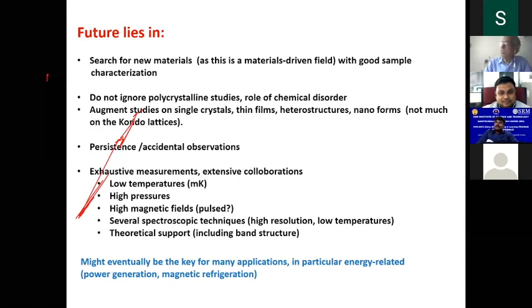But I would expect there is enough scope that one day some material will be found. There are also thermoelectric applications, particularly with these materials. By the way, I did not use the term strongly correlated electrons; they are all called strongly correlated electron systems. As I already mentioned, Kondo semiconductors like cerium copper arsenic 2 exhibit insulating or semiconducting behavior. Thermopower is large, thermal conductivity is large, but the figure of merit is still not so comfortable. It is hoped that by tuning the material, some will eventually turn out to be good, useful energy-related materials. I am sure there is enough scope because of electron correlations; one day this will lead to many materials and much more exotic applications.